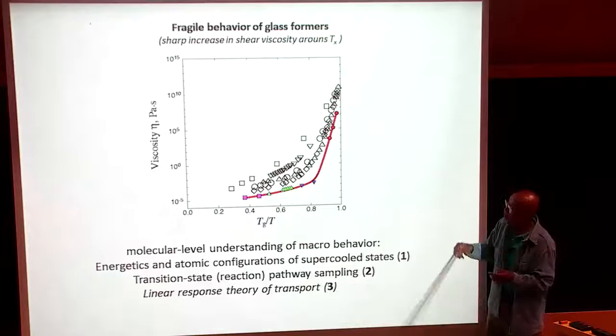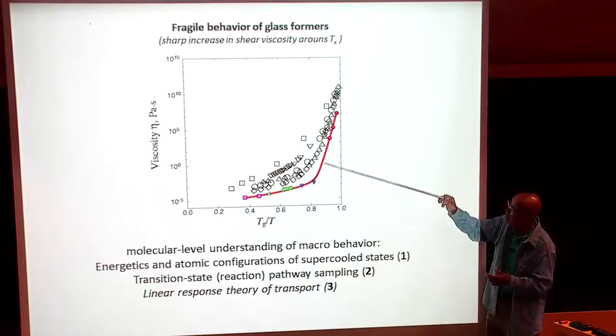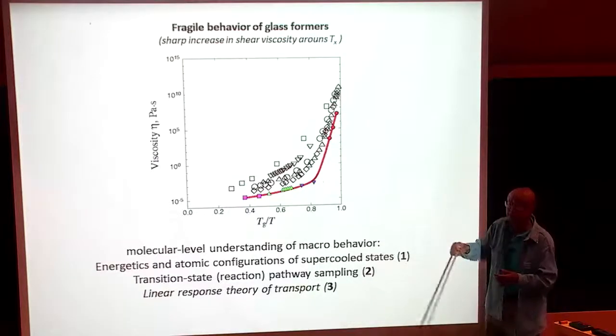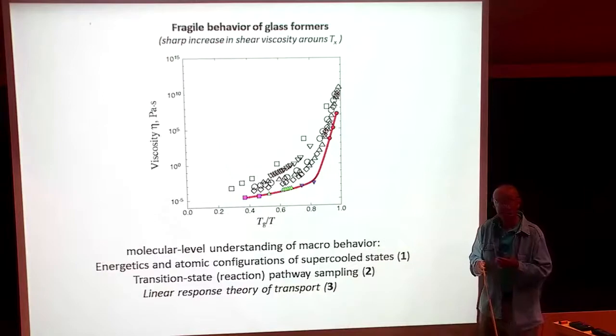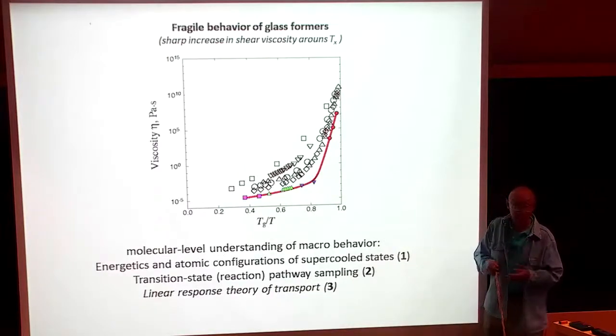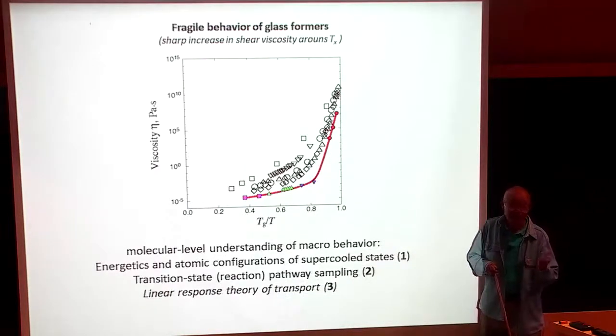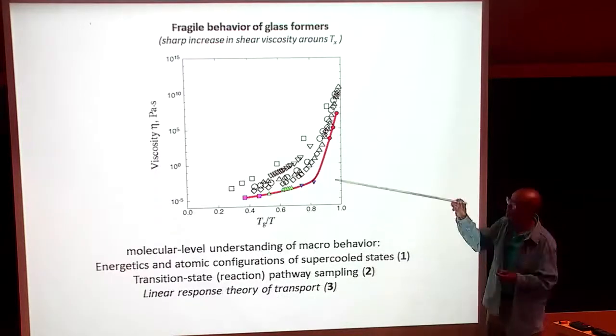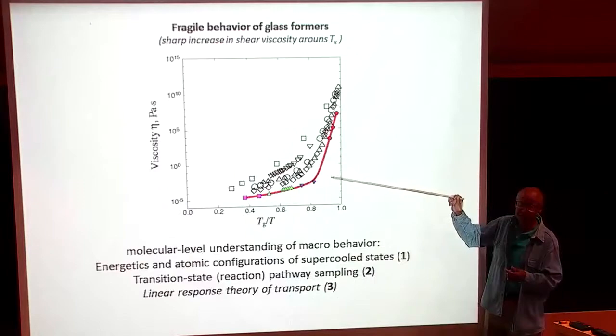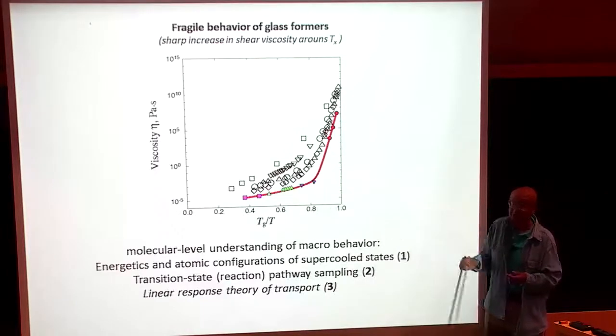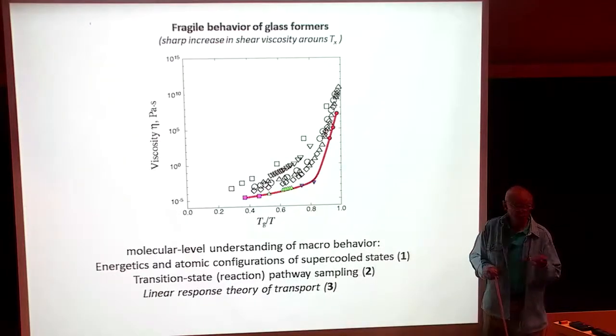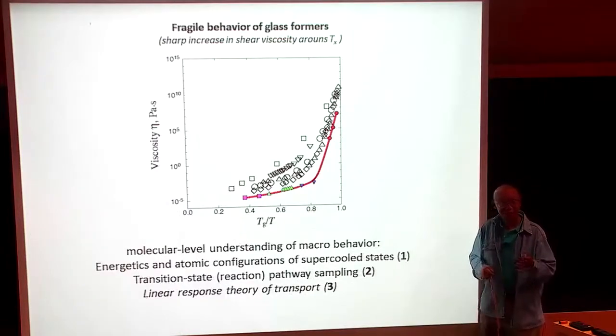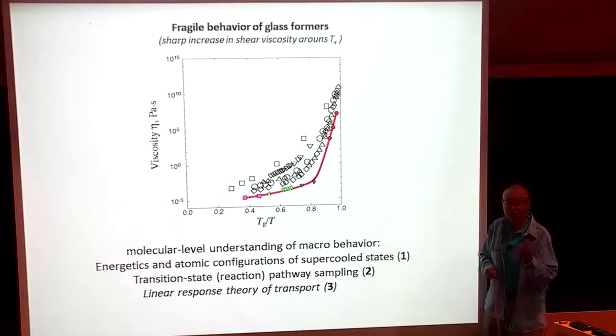That's why, once you get into this, one of the big problems in the glass community is, what's the quench rate? Well, quench rate is whatever you can do in the laboratory, for example. And therein lies a big difference between people who do simulation of glass transition and people who actually talk about the measurements. When you do simulation, you quench the system like crazy, 10 to the 7 degrees per second. That's a huge quench rate. Nobody does that in the laboratory.